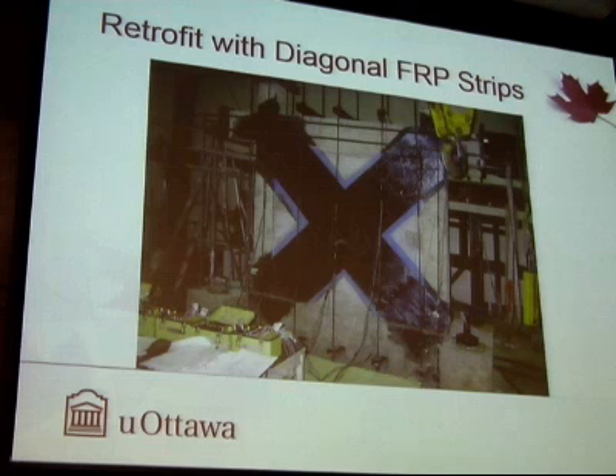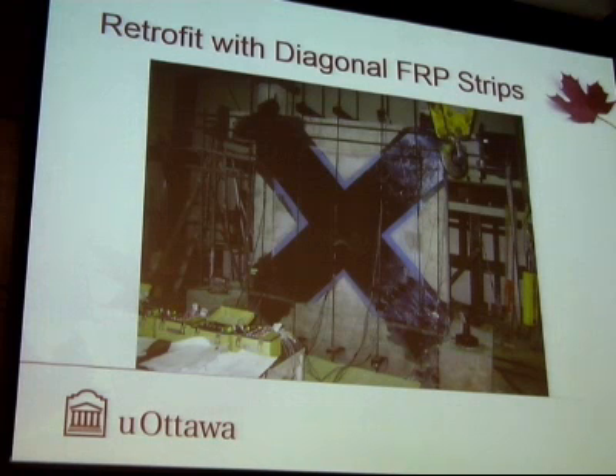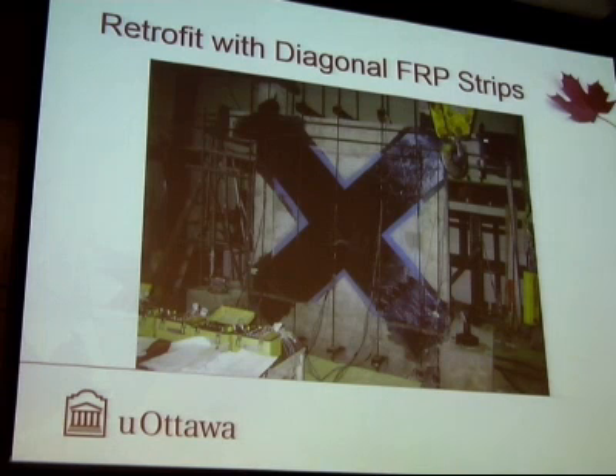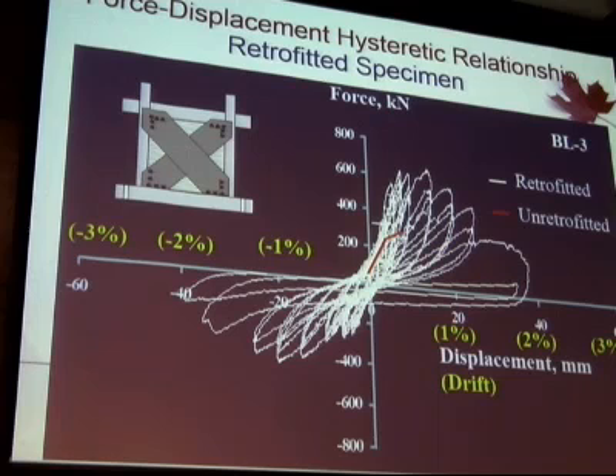Then there was much debate on the cost of this type of application, so we tried to minimize use of FRP. Since then, FRPs are becoming available at reasonable cost, and we used only a long diagonal tension, so X-bracing was the application. Everything else remained the same. In the previous application, of course, we had the side benefit of controlling infill walls against out-of-plane failures. This time there was that as well, but not as well as continuous coverage. And because total fiber area reduced this time, there was relatively lower strength gain, but this was still significant, at least double the unretrofitted strength.